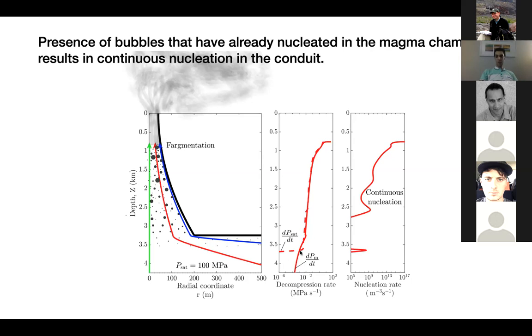However, as magma gets close to the conduit entrance, it accelerates, causing decompression rate to again pass diffusion rate. This results in the buildup of supersaturation pressure. As magma enters the conduit with a slightly converging cross section, it continues to accelerate. At some point, supersaturation is high enough that the second nucleation event starts. Due to the presence of pre-existing bubbles, this time diffusion rate and decompression rate are close to each other, resulting in a complex feedback between them that results in continuous nucleation that continues throughout magma ascent in the conduit until fragmentation.